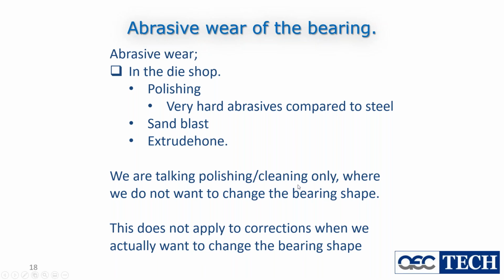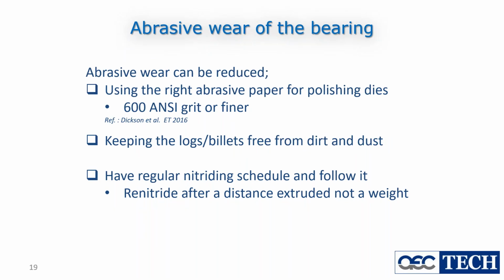If you want to change the shape of the hole, you want to move the bearing, put a choke on it, put a relief on it, or open up a gap, then you need more aggressive paper because you need to remove some steel. The theory behind using the lighter grade papers is you're only removing the dirt, you're not removing the steel. And since we want to keep the steel, that's good. But if you're going to do a die correction, basically you need to remove steel, so you use more aggressive paper. Quickly through then, use the right paper for polishing dies in the die shop.